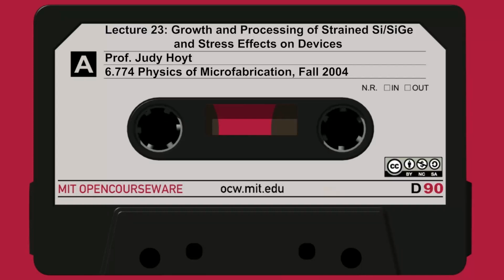What do these relaxed silicon germanium graded buffer layers look like? I said they have very few defects that thread to the surface. That's indeed true. These are some cross-section TEM micrographs of relaxed silicon germanium. See at 10%, this is the silicon substrate. This is the graded layer. There are lots of dislocations in the graded layer. That's what you want. You want dislocations down in the graded layer because you want to relax the lattice parameter. You want it to expand to its equilibrium parameter.